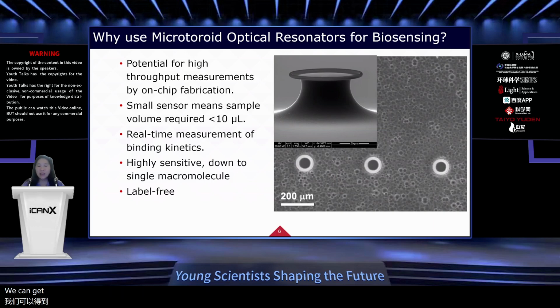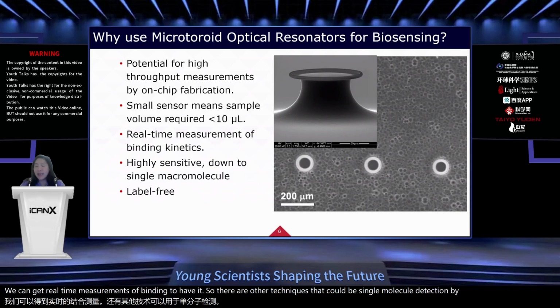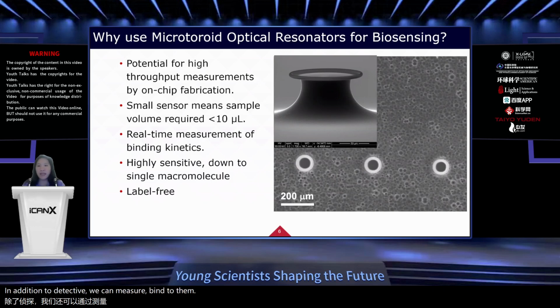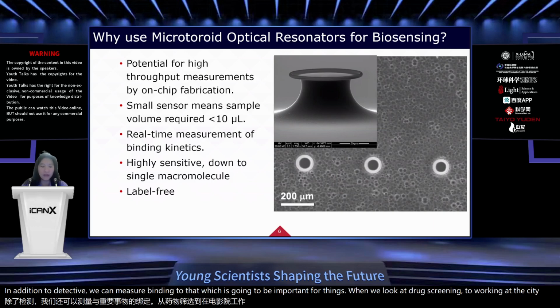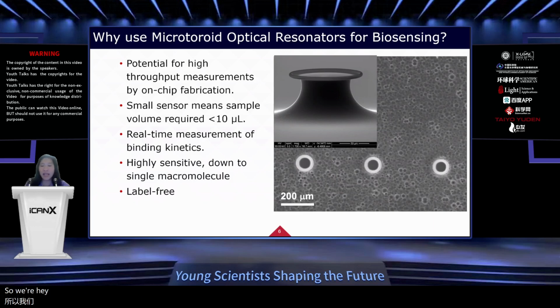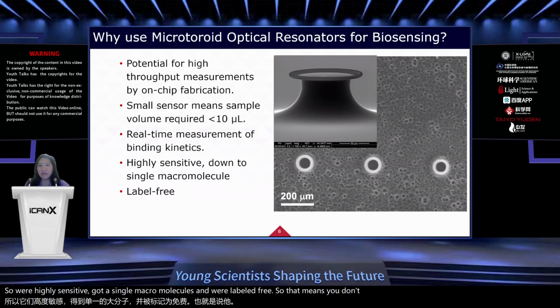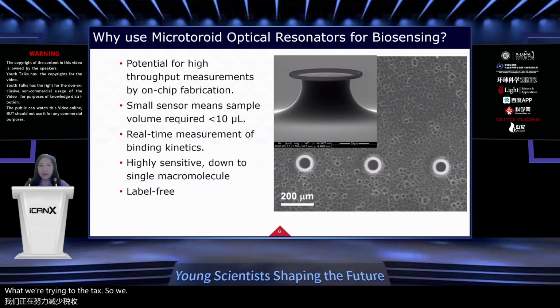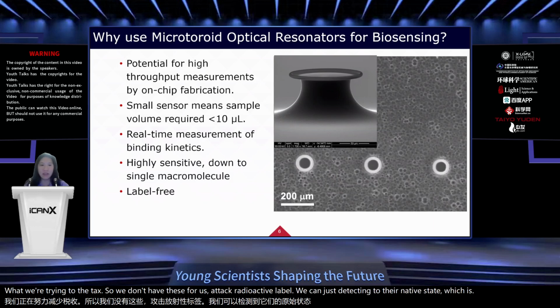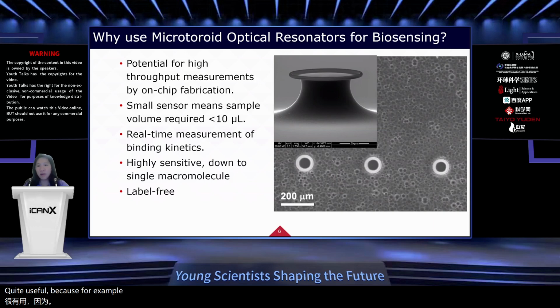This is really important if you have samples that are precious or hard to get. We can get real-time measurements of binding kinetics. There are other techniques that can do single molecule detection, but in addition to detection, we can measure binding kinetics, which is going to be important when we look at drug screening. So we're looking at the affinity of different drugs binding. We're highly sensitive down to single macromolecules, and we're label free. That means we don't have to label what we're trying to detect, so we don't have to use a fluorescent tag or radioactive label. We can just detect things in their native state, which is quite useful because, for example, when we're looking at small molecule drug discovery, it's not always possible to tag those drugs.